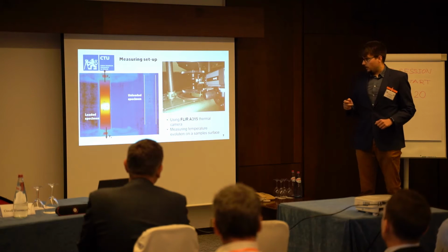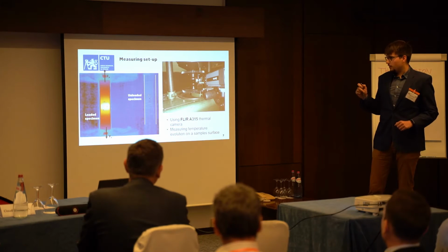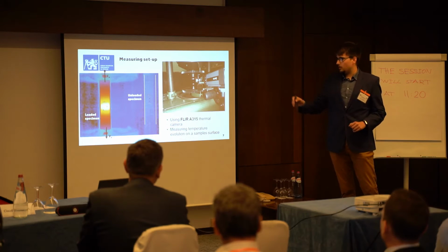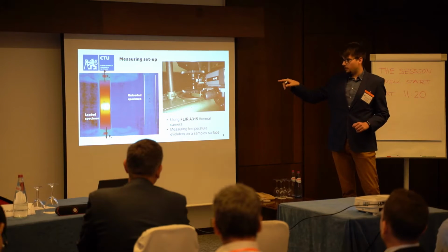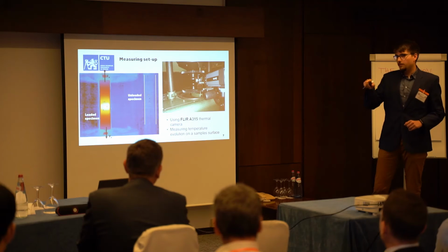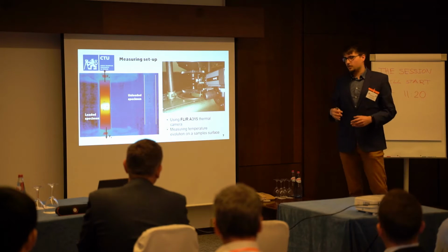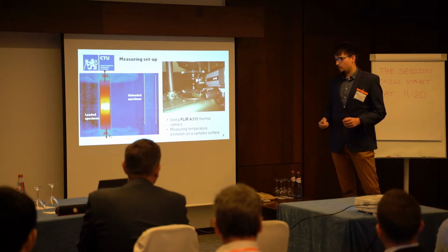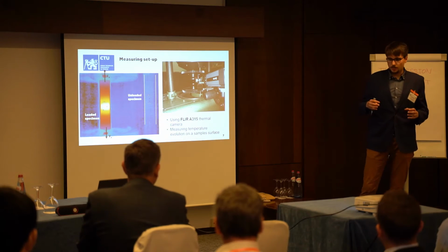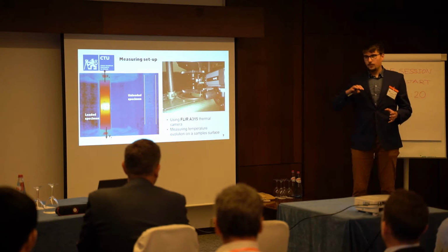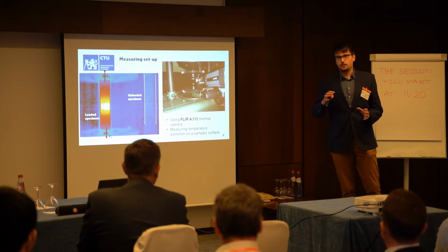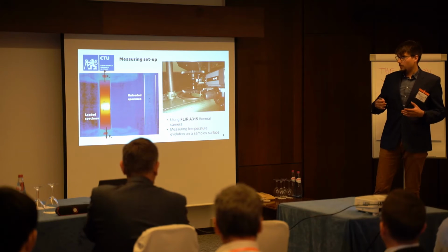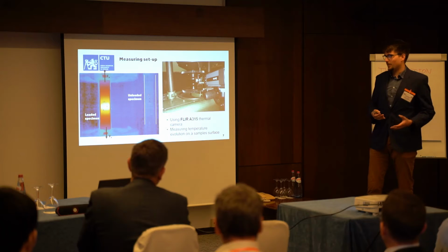Also, this needs to be pointed out that we are measuring the loaded specimen, which is loaded by the amplitude of load, and you can see the focus area in the middle. It varies with the geometry of the sample, but there is also an unloaded specimen which can be used as a correction of the deviation in the chamber where the testing is happening.